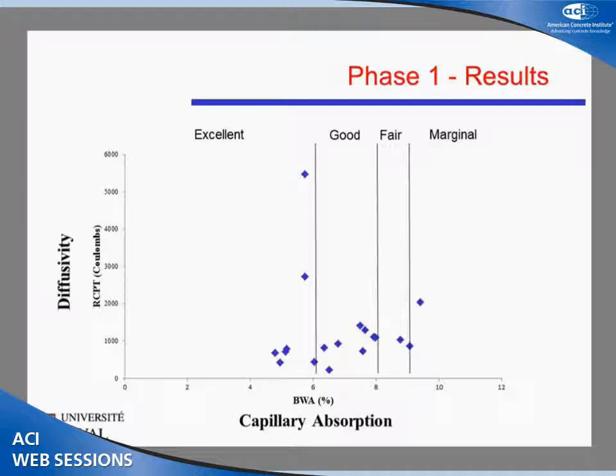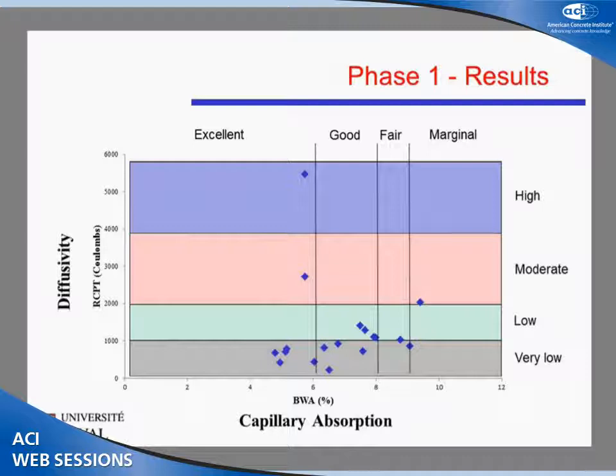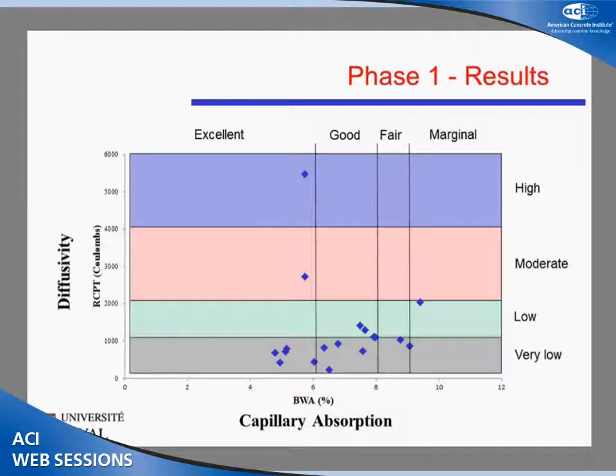So at first sight, we see that there is no direct correlation between the two tests. But to go a bit further, what you see here are limits that we found in ASTM C1202, the RCPT standard. And those are limits that indicate the chloride ion penetrability. I want to bring your attention to two things. If you look at the strip below the gray zone, you can have results, with the boiled water absorption results ranging from marginal to excellent. On the flip side, if you look at the left vertical strip, you can have all mixtures that would have been qualified as excellent for their boiled water absorption results, but their chloride ion penetrability ranges from very low to high. So this graph is very important, because two situations can occur.